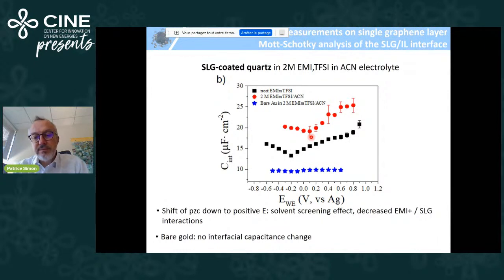What does it mean? It means that simply you decrease the EMI+ cation graphene layer interactions just because you add solvent. If you remember what I just mentioned before, you have strong interactions between the cations and the single layer graphene in neat EMI TFSI, and this strong interaction was responsible for a charge storage mechanism by ion orientation onto the graphene surface during negative polarization.